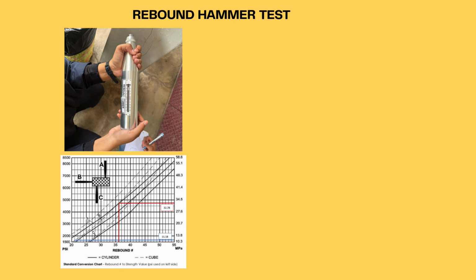The rebound hammer test was conducted on two sides of the selected concrete structure to evaluate the surface hardness and estimate the compressive strength. Based on the results, side 1 recorded an average rebound number of 21, corresponding to an estimated compressive strength of 11.18 megapascal, while side 2 recorded a significantly higher average rebound number of 36, indicating an estimated compressive strength of 32.78 megapascal.